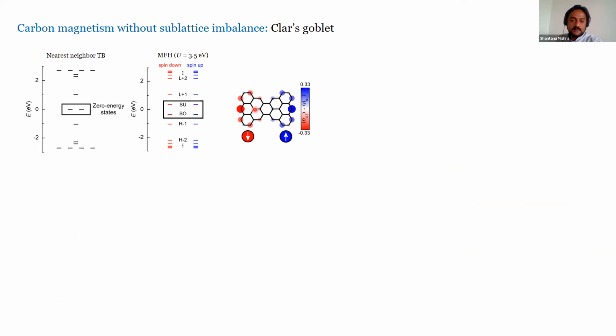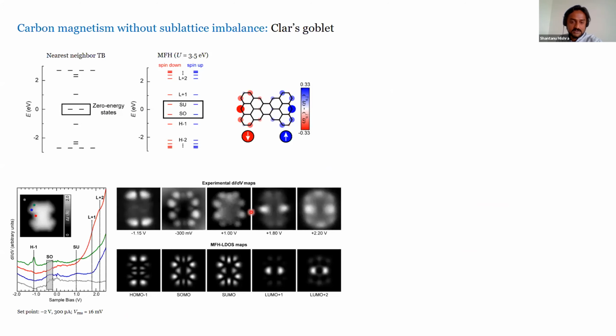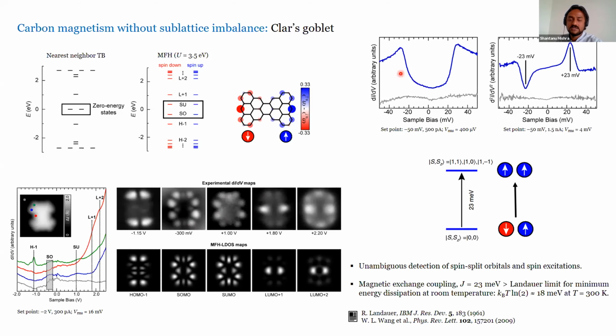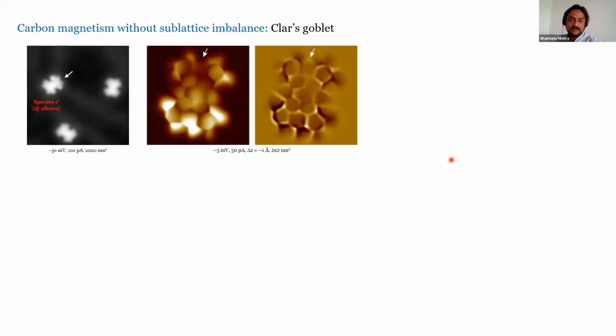So now you have spin down on the left side, spin up on the right side. You do a long range spectra and you again find the SOMOs and the SUMOs. Not only that, now you go close to the Fermi energy and you find spin excitations. And these spin excitations are singlet, which is the ground state, to triplet. And if you see, the energy of these spin excitations is 23 meV, which is actually quite close to the room temperature thermal energy. My final slide is to prove that these are indeed spin excitations.